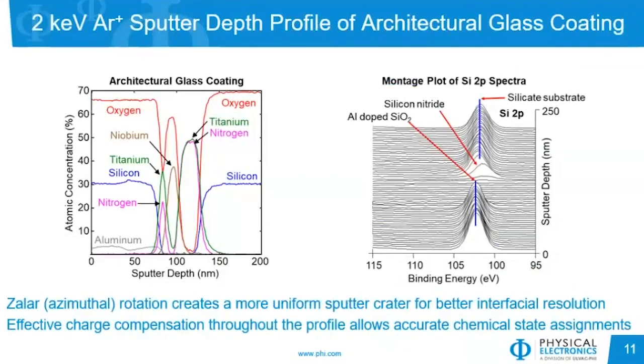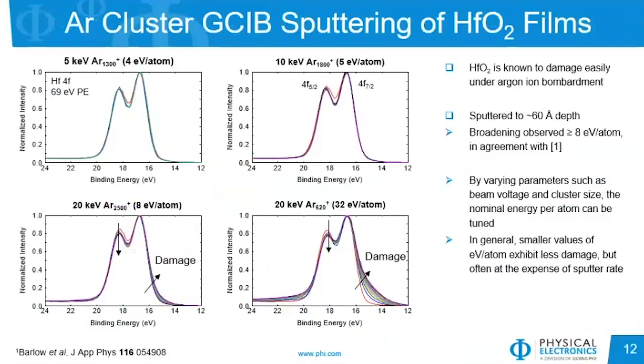We can also use higher energy argon for things like sputtering through a multi-layer glass coating. As you can see here, we have multiple layers, and we have very nice interface resolution as we go through the layers. In the spectra on the right side, we see that slight changes in the Si2P correspond to the aluminum-doped silicon oxide near the surface and the silicate substrate. This also shows how we can use additional properties of our profiling, like Zalar rotation, which allows us to rotate the sample during a profile to get a more uniform sputter crater and enhance the interface resolution. We also see that we can use our dual beam charge compensation during this profile to get accurate chemical state information for peak assignments.